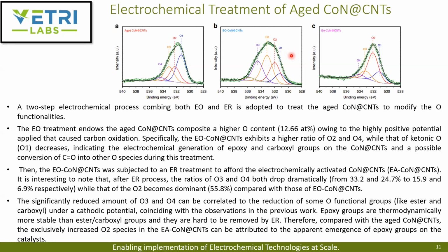First they did the electrochemical oxidation treatment, and as we can see here, the cobalt nitrogen doped composites have a higher oxygen content, 12.66 atomic percent compared to 5 atomic percent, because we apply a high positive potential. In specific, apart from the O1, the ketonic group, the O2 on the epoxy and the carbonyl oxygen exhibited a higher ratio. However, the ketonic oxygen decreased, indicating the electrochemical generation of epoxy and carbonyl groups on the cobalt nitrogen doped CNTs, possibly converting the ketonic group into other oxygen species during this treatment, since we are further oxidizing it.